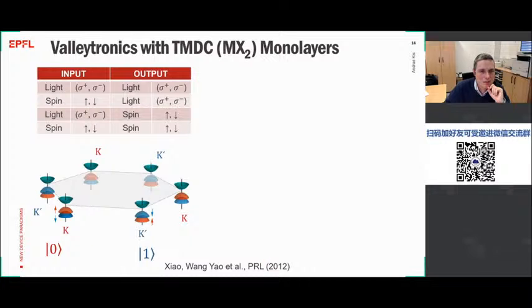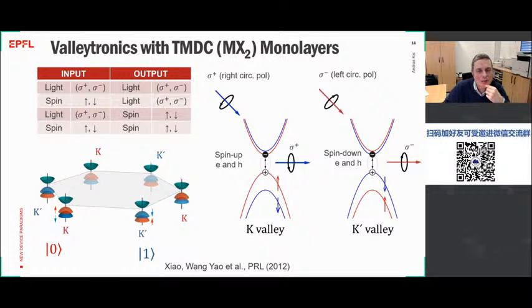And the first is that these valleys could be easily addressed optically. So if you look at these 2 points, I have here a more magnified view. You can address one or the other valley by shining circularly polarized light with right or left polarization. And then this would generate excitons inside the material. And when the excitons would recombine, they would emit again light with one or the other circular polarization, but this would be the same circular polarization as the light that came in if we have this valley polarization preserved. So by choosing the light polarization, we can select the valley.